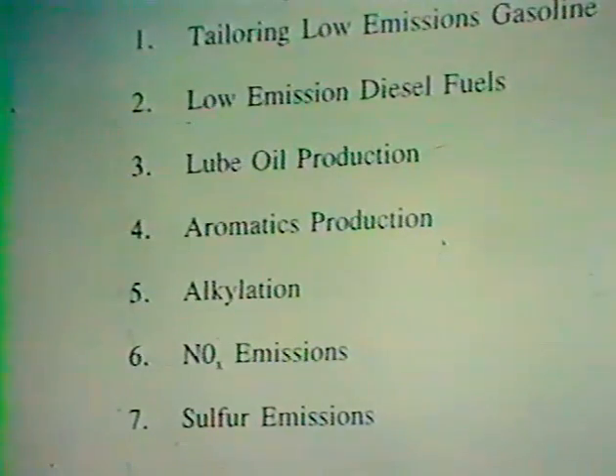Alkylation is an area which is effective at the moment. We're trying to get away from sulfuric acid and hydrogen fluoride catalysts toward solid state catalysts because of pollution control and disposal problems. Here I'm referring to aromatics alkylation, benzene in particular, and I think we're in pretty good shape now. We've got away from aluminum chloride and phosphoric acid, and these are being replaced by Mobil processes using ZSM-5 catalysts, and a system out of our laboratory at Lummus, which uses a modified Y zeolite-like catalyst for producing ethylbenzene and cumene.